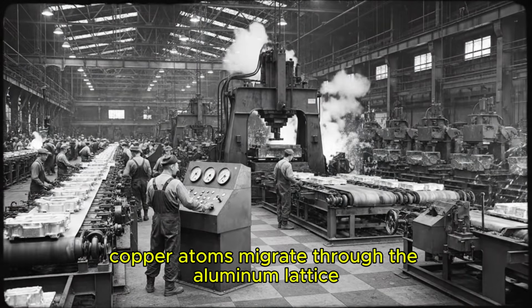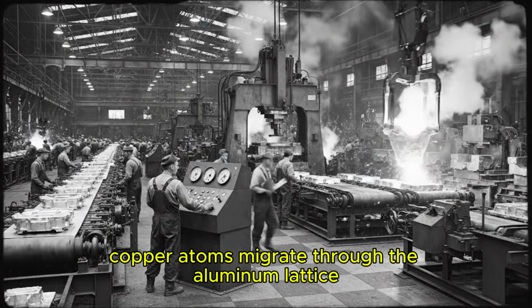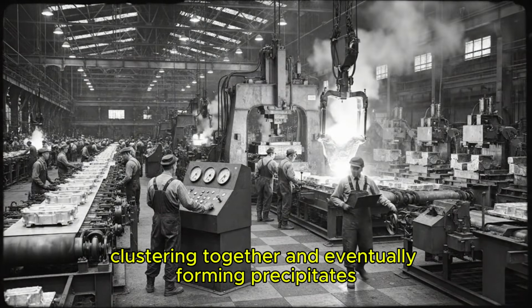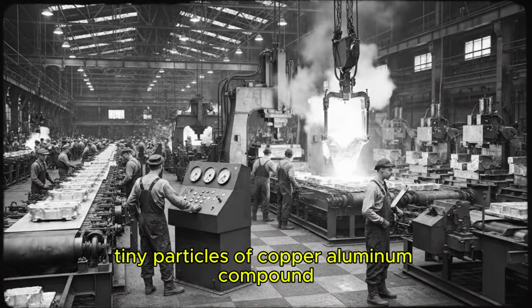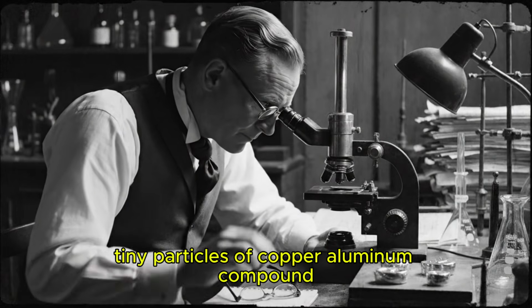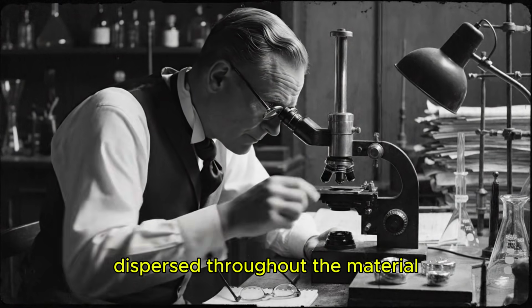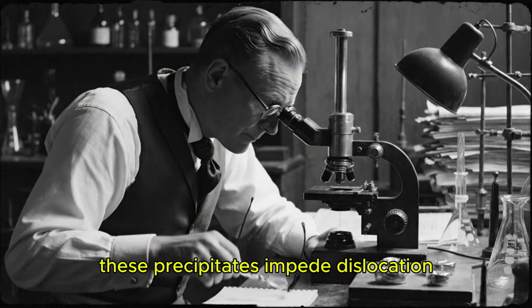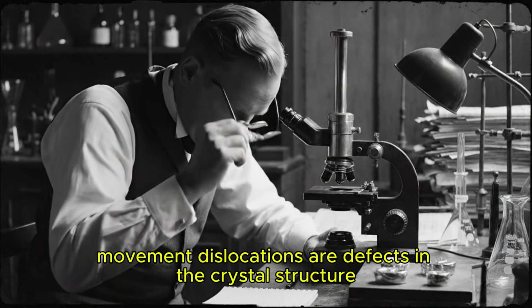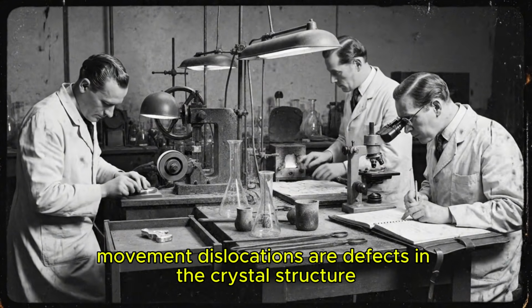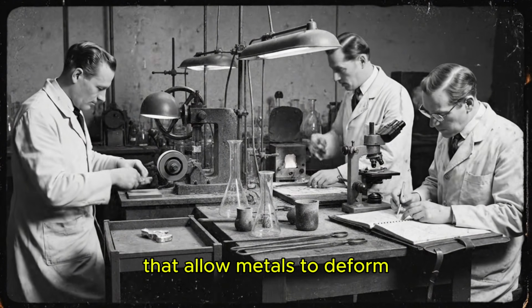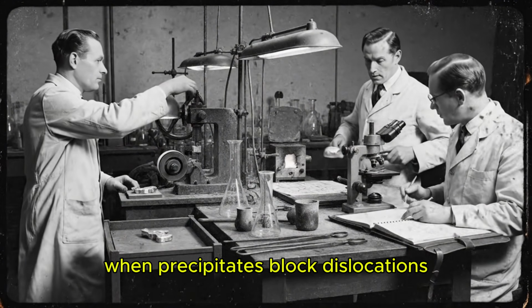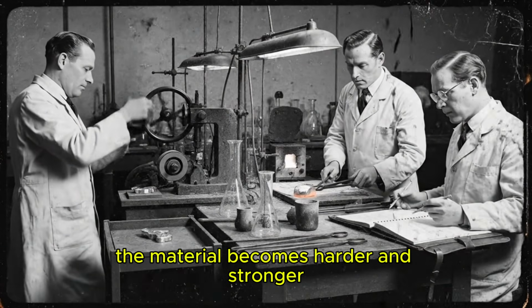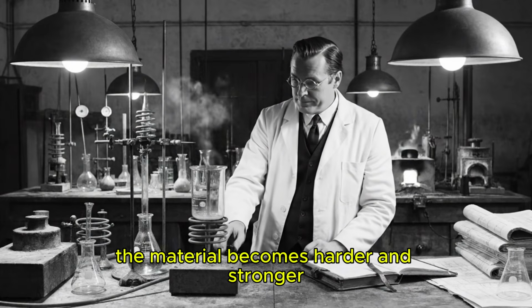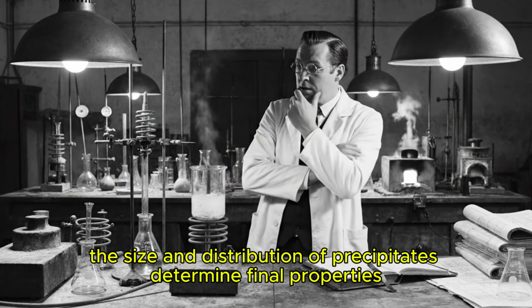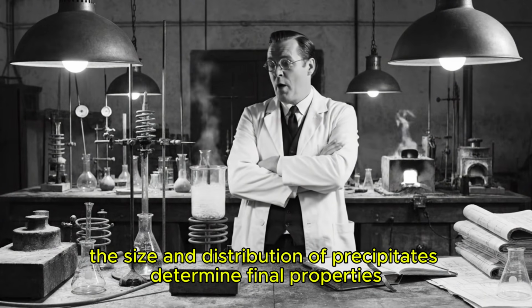Over time, copper atoms migrate through the aluminum lattice, clustering together and eventually forming precipitates, tiny particles of copper-aluminum compound dispersed throughout the material. These precipitates impede dislocation movement. Dislocations are defects in the crystal structure that allow metals to deform. When precipitates block dislocations, the material becomes harder and stronger. The size and distribution of precipitates determine final properties.